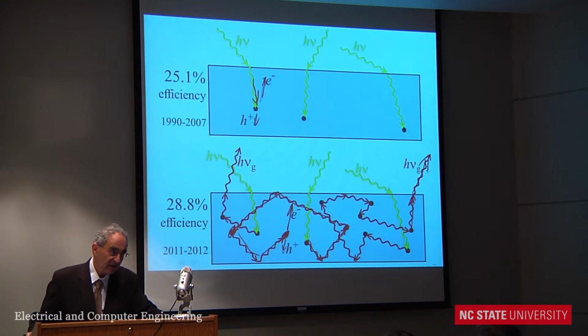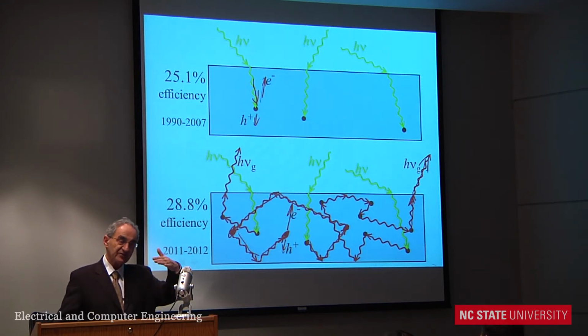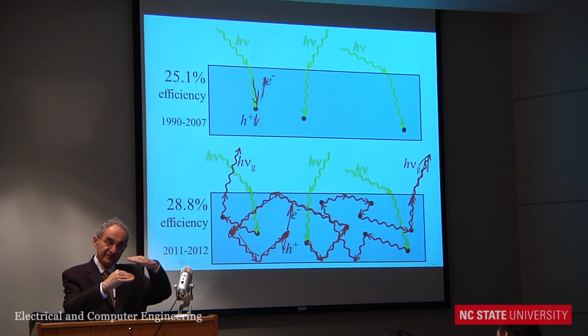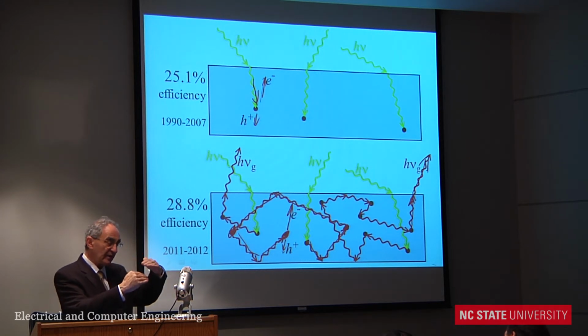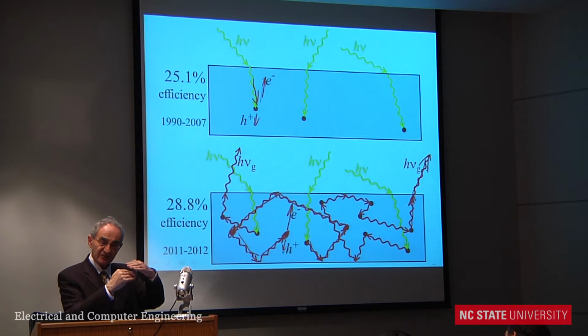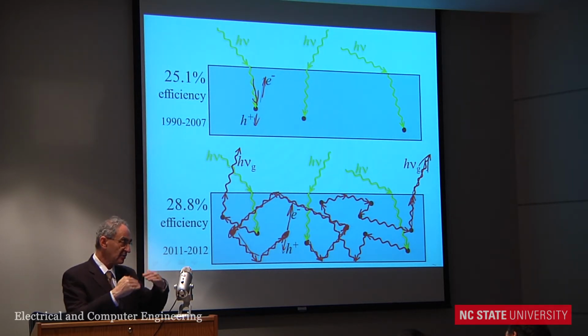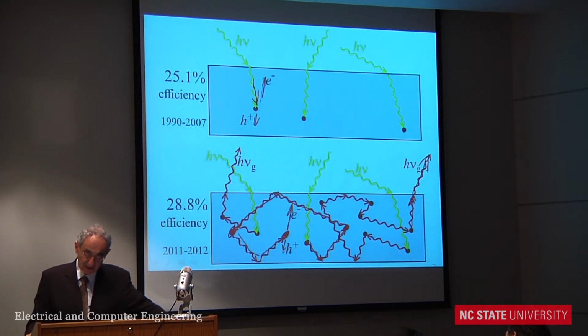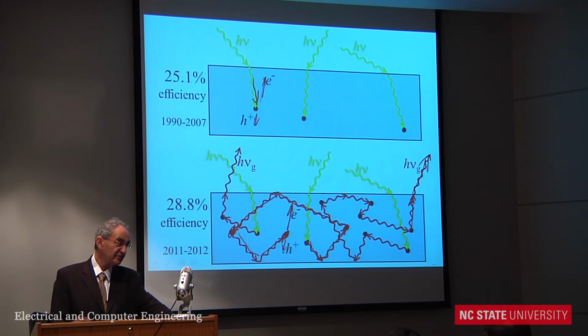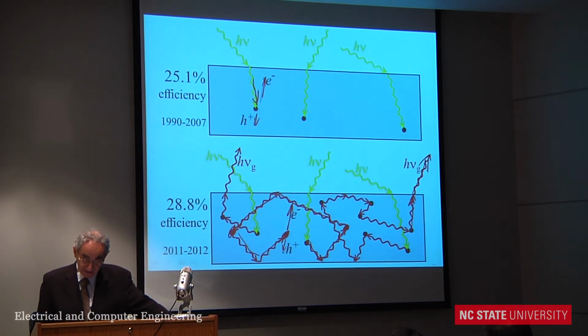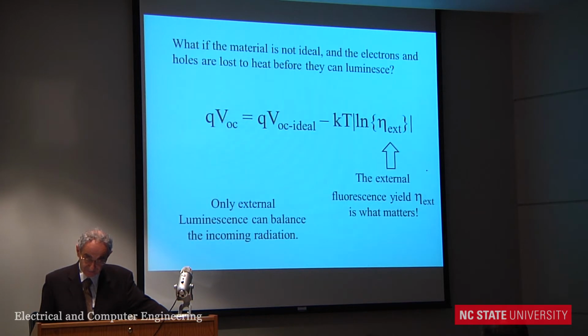In this picture, when the sunlight comes in, you might have one sun falling on the cell, but if that cell is a high-performance cell, you will trap 30, 40, or 50 suns of infrared luminescence inside. And that's a requirement for breaking records and for getting close to the Shockley limit. And so it's a very different picture. And a lot of that luminescence is trapped inside and is constantly being recirculated. And it's a necessity for achieving the high efficiency.